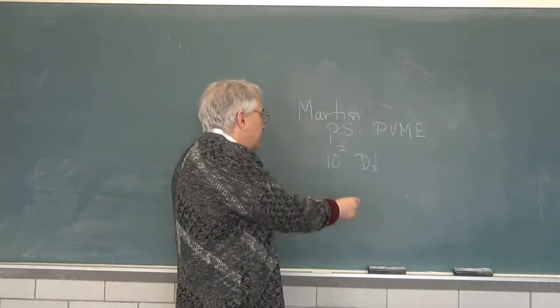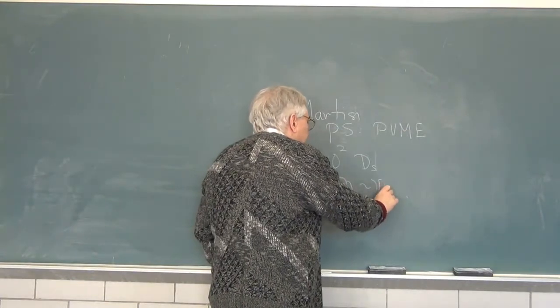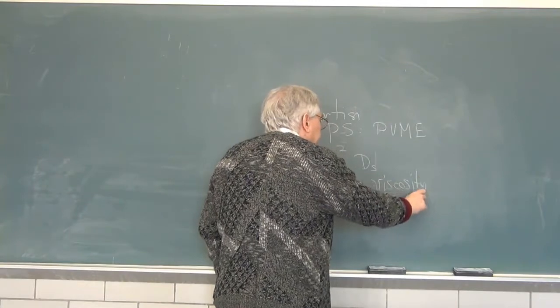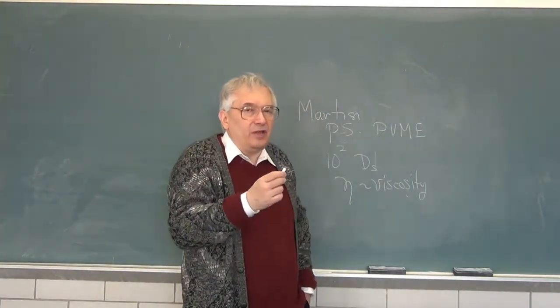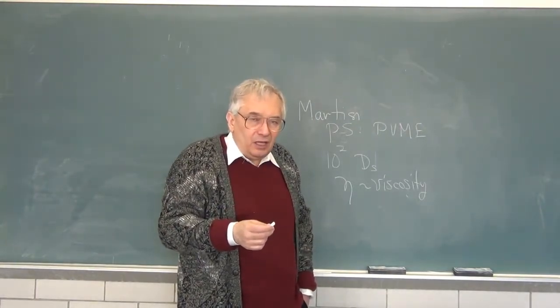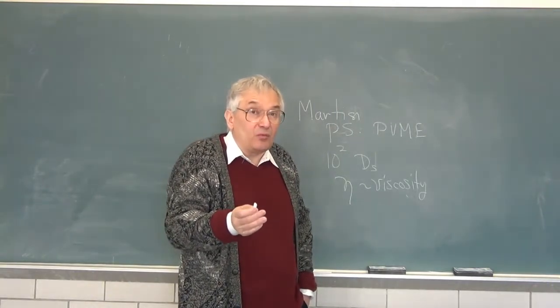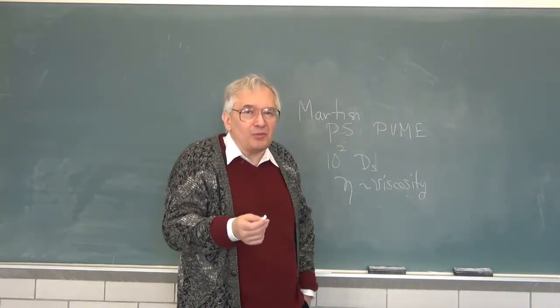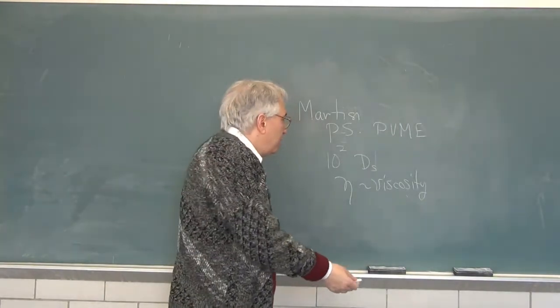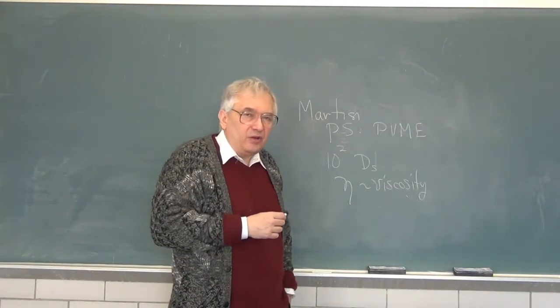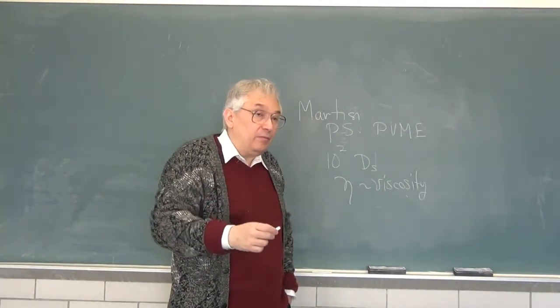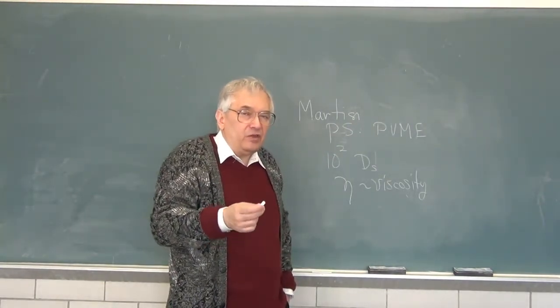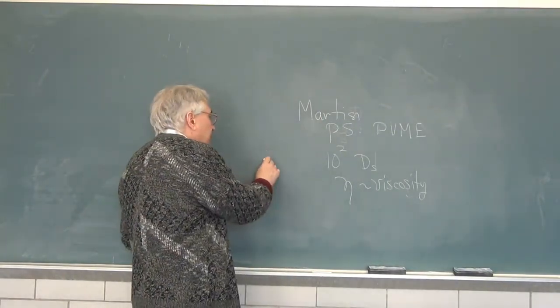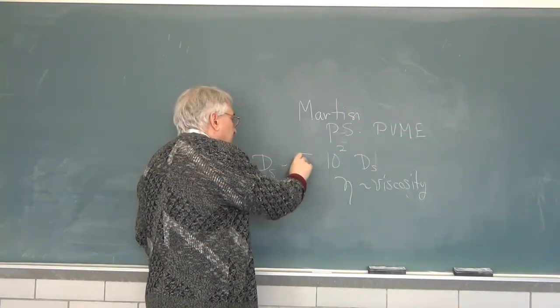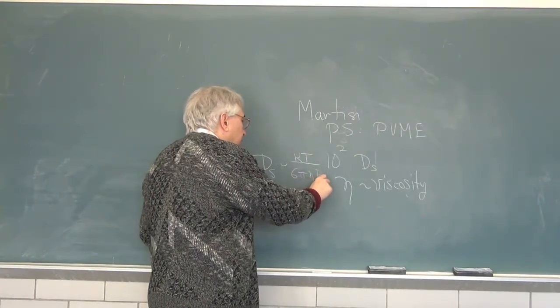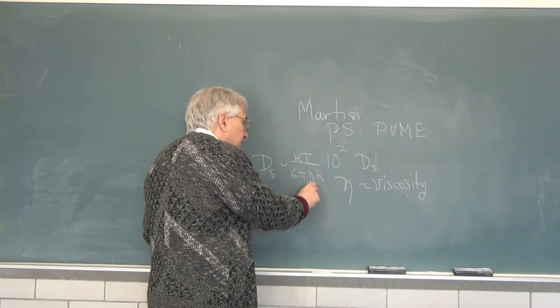However, Martin did something else. In addition to measuring DS, he also measured eta, the viscosity of the solution. The issue with solution viscosity is that if you have a solvent and you start stirring polymer in, almost all cases, as you add polymer, the solution becomes more and more viscous. And you might say that there is some approximate resistance to flow, and that approximate resistance to flow should perhaps correspond to a change in the diffusion coefficient. If you have mesoscopic spheres, say 20 nanometer spheres, diffusing through a small molecule liquid, then you quite uniformly find DS proportional to kT over 6 pi eta r, where eta is now just the solvent viscosity, that's all you have.